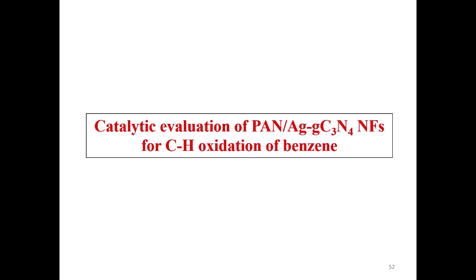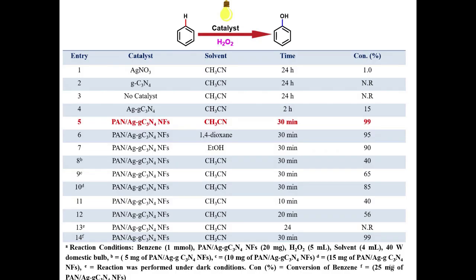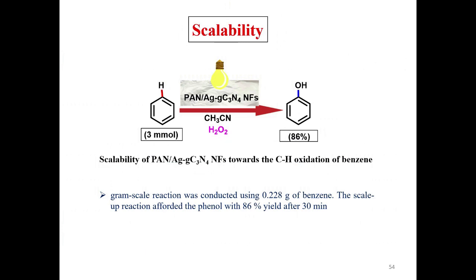Now we look into the CH oxidation of benzene. So here benzene, when it reacts, gives phenol, again under the same condition, PAN-Ag-gC3N4 in presence of methyl cyanide as solvent. 30 minutes time we require, and 99% conversion to phenol is there. This is the scalability of the reaction. A gram-scale reaction was conducted using 0.228 gram of benzene. The scale-up reaction afforded the phenol with 86% yield after 30 minutes.